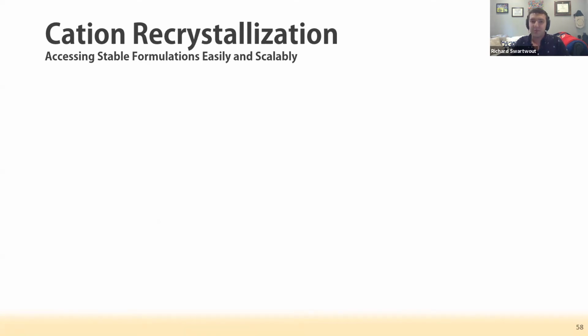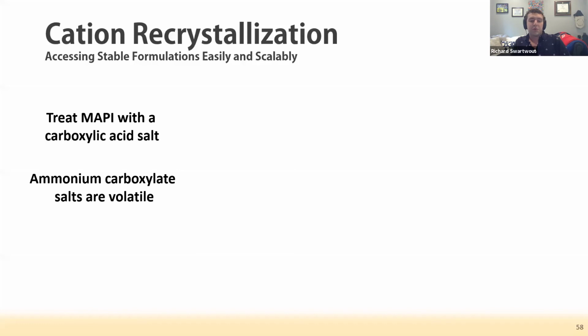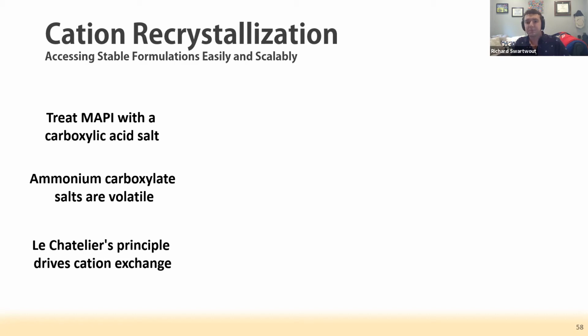The process is very simple. We take our printed MAPI film as shown in the previous video. We treat it with a carboxylic acid salt of a cation of interest, or a mixture of cations of interest. Ammonium carboxylates, and specifically methylammonium carboxylates, are generally either volatile, easily degraded with heat, or ionic liquids. And so under heating, these volatilize off the film. Through Le Chatelier's principle, cation exchange is chemically driven into the film.